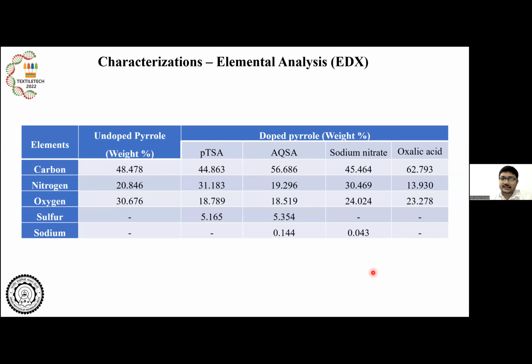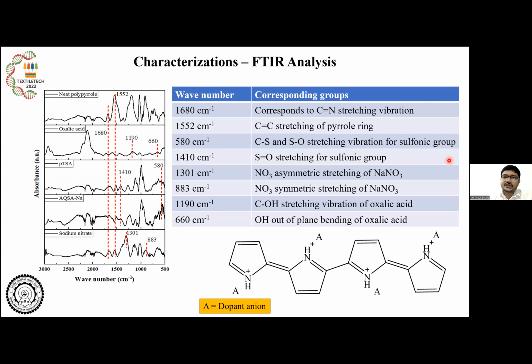For confirmation that these compounds are present within the polymer, EDX analysis was done, and sulfur contents were observed in case of PTSA and AQSA, and the higher percentage of nitrogen and traces of sodium confirmed the presence of sodium nitrate. In case of oxalic acid, the only confirmation was higher carbon content, since it leaves the system and becomes carbon dioxide. Further confirmation using FTIR was done, and the stretching peak at 1410 confirmed the presence of sulfonic groups, and the 1301 and 883 peaks confirmed the presence of nitrate ions, and a few traces at the 1190 peak confirmed the presence of oxalic acid, that is, carboxylic acid formation.